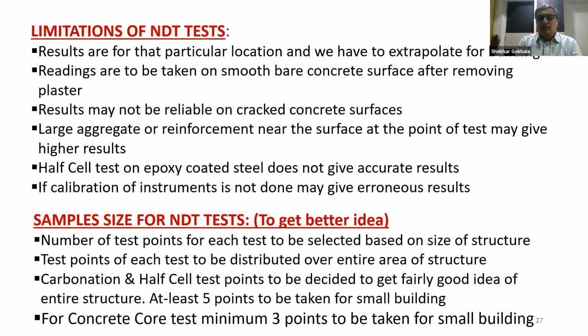and we have to look from the proper perspective, from visual inspection as well as NDT. We have to take all things together and then extrapolate results to the entire building. Sometimes we get good results in rebound hammer, but bad results in ultrasonic pulse velocity. So if there is quite a big variation in both the results, then we normally go for the core test, and based on the core test, we decide the fate of the building.